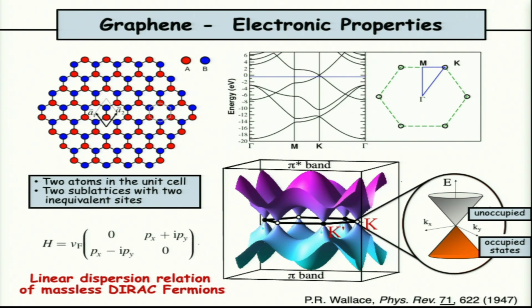And so if you look at the electronic properties of this system, you have the band structure here, and if you look at the K point in the reciprocal space, so this is the Brillouin zone, the hexagonal Brillouin zone of graphene, you have the K point, and if you look carefully here, you have a linear dispersion for the electronic bands in this system, which is quite unusual in solid state physics. And this linear dispersion allows to mimic, in fact, a kind of Dirac massless fermions in solid states, and so you can use this type of Dirac Hamiltonian to really mimic the system in this situation.